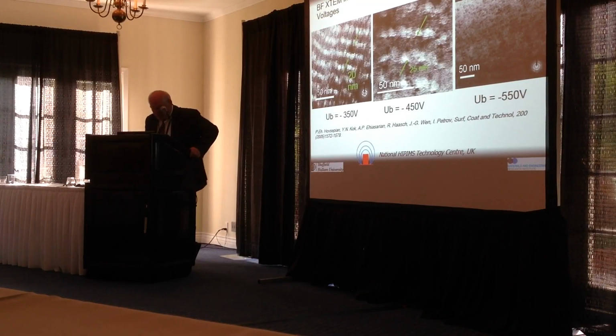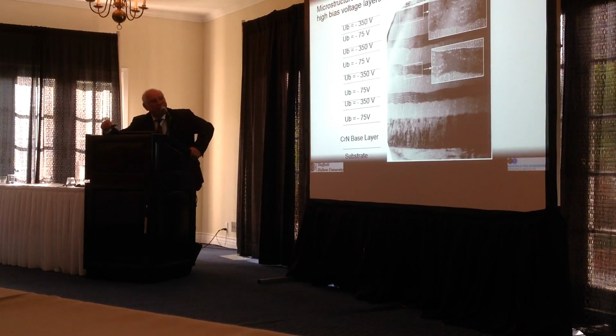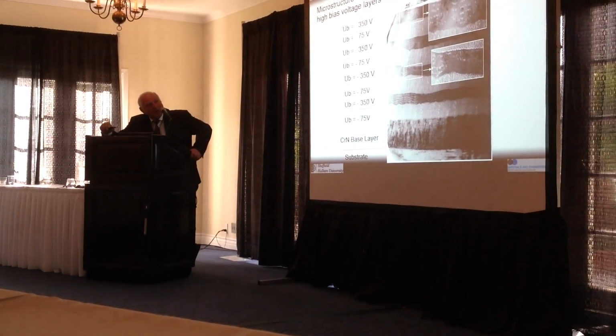So that was a very interesting growth based on carbon segregation, and you can actually show very clearly this based on the irradiation effects, because this sample was produced in one deposition run. For half an hour the coating was deposited at 75. In the next half an hour at 350. You reverse it to 75 and you reverse this structure. It is very reproducible. You can see all the signatures of the ion bombardment. Low ion bombardment, you can see the tops of the columns, very rough surface. High ion bombardment, this is the end of the cycle, very smooth surface because of the resputtering. And you can clearly see that you can just switch from amorphous to this layer structure absolutely accurately.